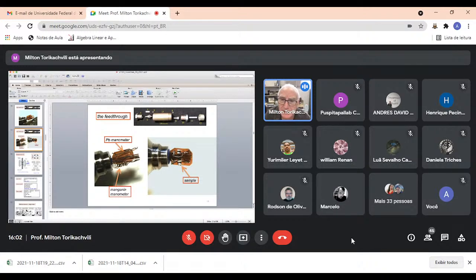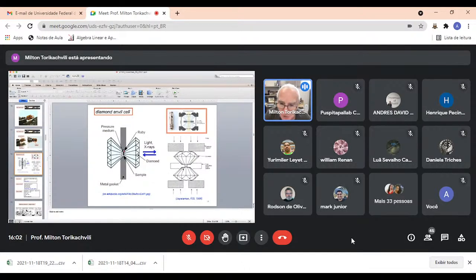Just to give you an idea, this distance here is about 4 or 5 millimeters. This is about 2 or 3. So all this work to put leads and attach the sample has to be done in a microscope. And still, this cell is much, much bigger than the diamond anvil cells that I want to show now. Probably this is the best drawing that I can show you here for how the diamond anvil cell works.